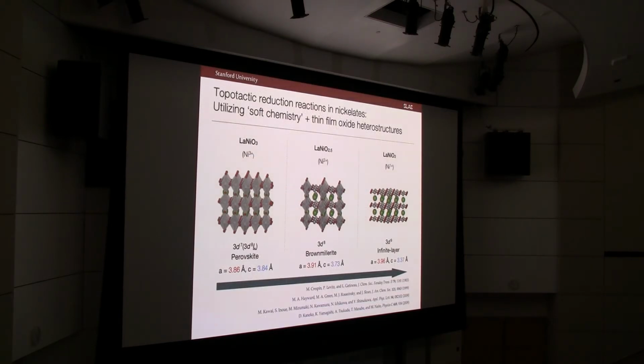So we're really relying on very creative chemistries that have been developed over the last few decades. And I'll just illustrate to you the way this works. The first experiments were done by taking powders of the perovskite form of nickelate. So this is a 3D perovskite oxide. Here's the crystal structure with nickel nominally in the 3+ state. So you have to synthesize this at high pressure.